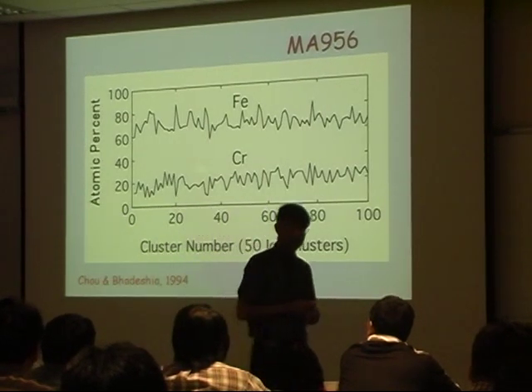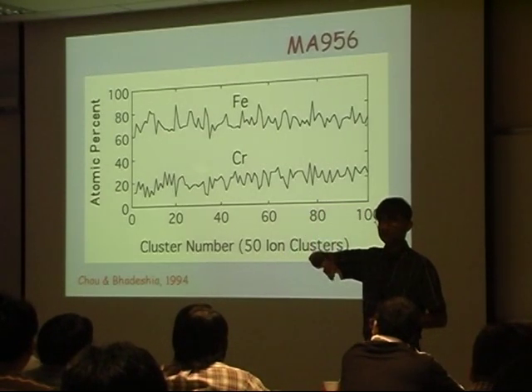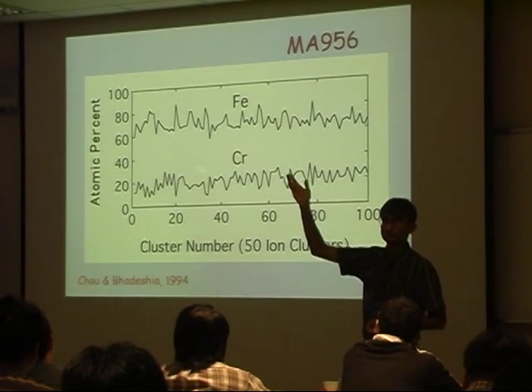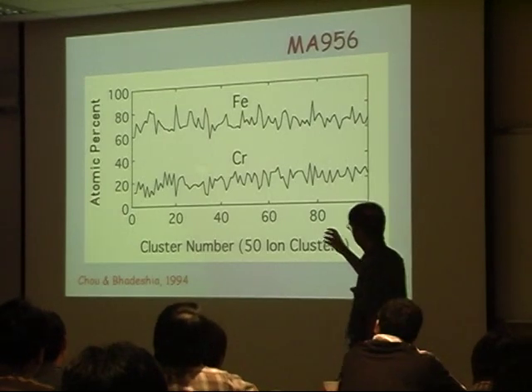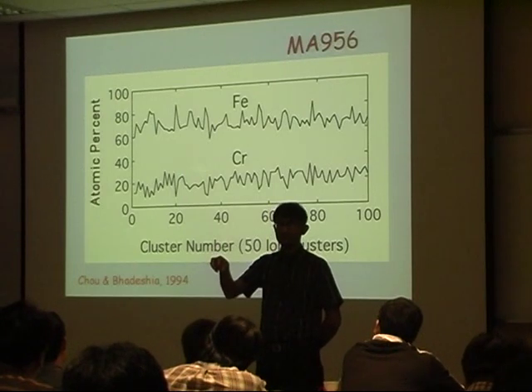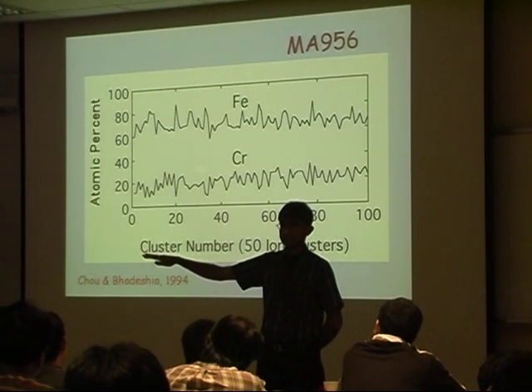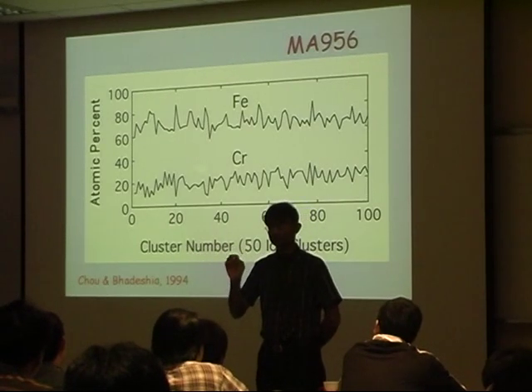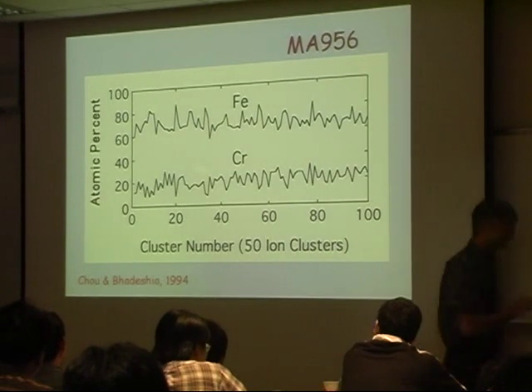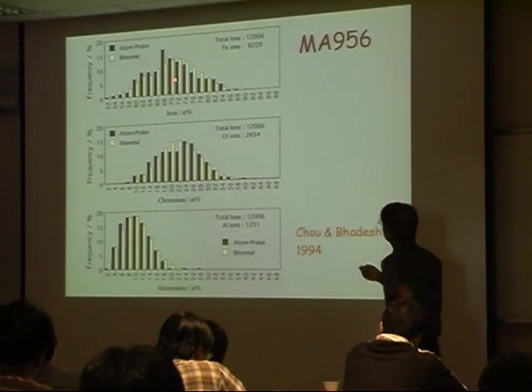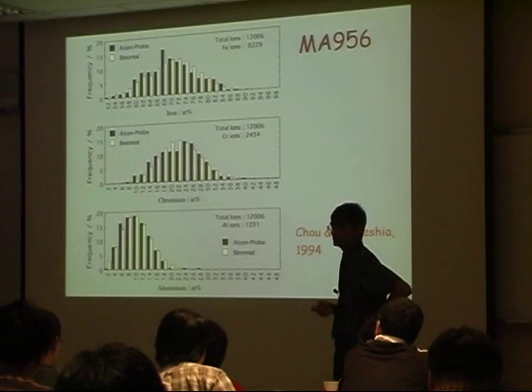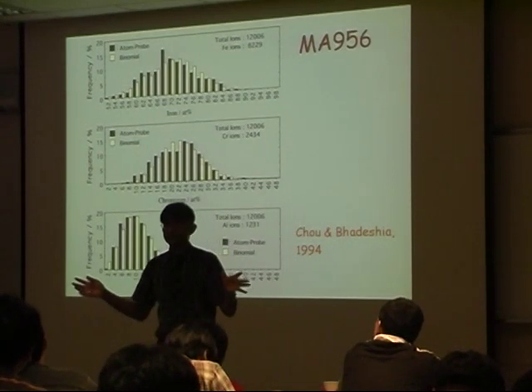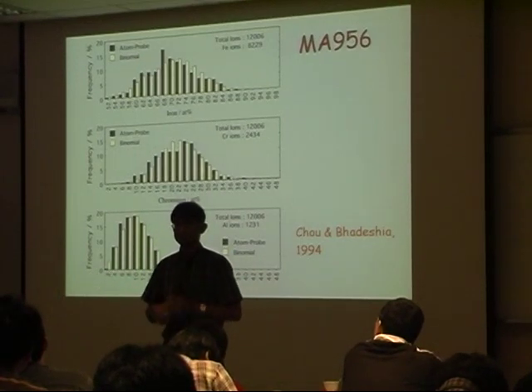It's very difficult to answer this question, because when we analyze atom by atom we get a variation from 0% to 100%. If I analyze the average composition of two atoms, I could go from 0% to 50% to 100%. What we have to do is say: if I pick out 50 atoms from a completely random solution, what is the distribution of compositions I would expect? That's called a binomial distribution. This is exactly like opinion polls — if you took one voter in the USA and asked whether they're a Bush or Kerry voter, you can't assume 100% of the population votes that way.